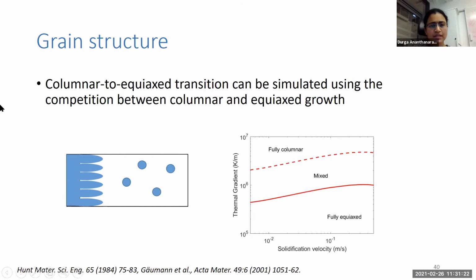There are different ways we can do this. But from a modeling perspective, what we want to look at is the competition between the columnar growth and the equiaxed growth. Imagine that this is the bottom of the melt pool, and you have the start of these columnar grains. They grow into the melt pool. Suppose there are effective nucleating sites here for equiaxed growth, then they would also start growing. Whichever wins, that structure is predominant inside your melt pool.